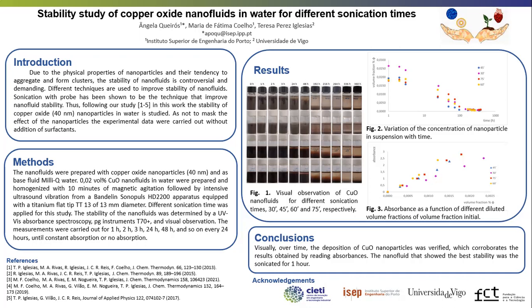In figure 2, it is possible to observe that for 1 hour of sonication, the behavior is more stable when compared with other sonication times. It means that it preserves the initial concentration for a longer time, and thus the nanoparticles remain in suspension. Figure 3 shows that as the sonication time increases up to a certain time, the absorbance increases. That is, the absorbance is greater when the concentration of nanoparticles in suspension is greater. Thus, the highest absorbance corresponds to the optimal sonication time.